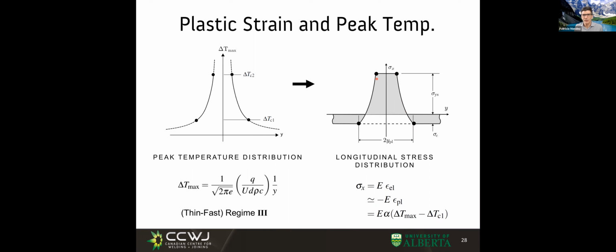I want to be clear, this width here is not the width of the weld bead. This width here is the width of the isotherm of 200 degrees. The width of the weld bead is the isotherm of 1500 degrees. This one is the isotherm of 200 degrees. This is much, much bigger. This compressed part in a big plate is negligible. So we can forget about this part now, because it's just the part in compression.